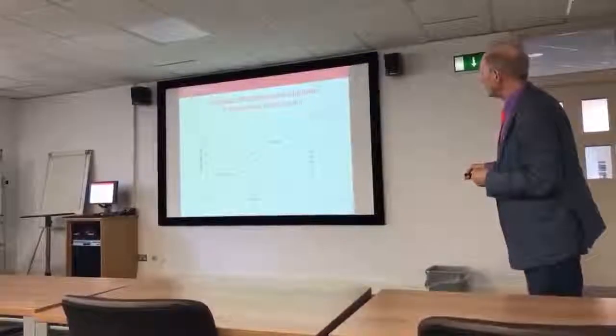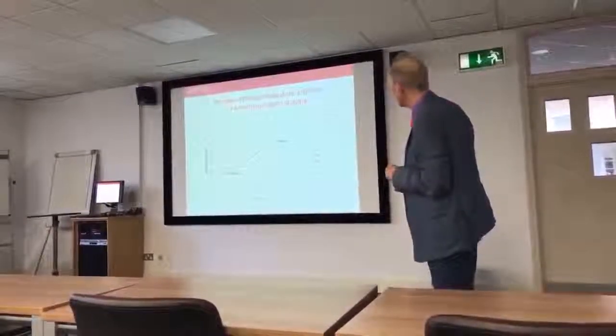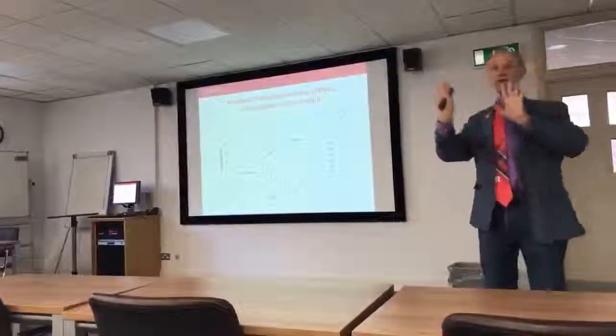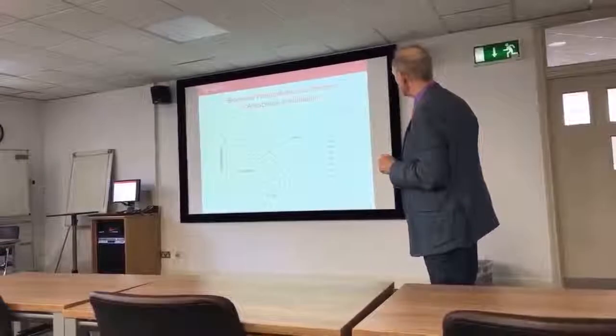This is the average lifetime of riboflavin in a series of sugars from maltose, maltotriose, etc., up to maltoheptose. So 2, 3, 4, 5, 6, 7. These are synthetic, so they're exact. And what I've done is I've plotted lifetime not versus temperature, but normalized to the TG. Because what I'm really interested in here is getting at a signal which will tell me what's happening in either the glassy or the rubbery state of this amorphous material. And what you see is that there's a very characteristic trend that at any given temperature below TG, as you go to a larger sugar, the lifetime goes down.